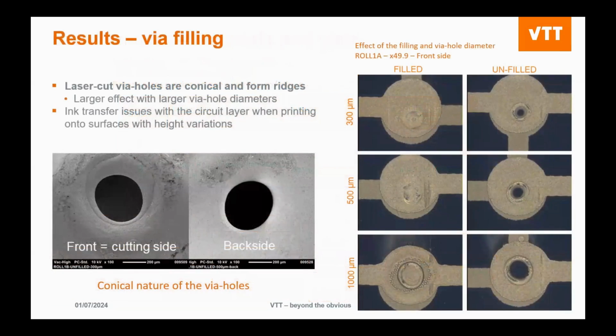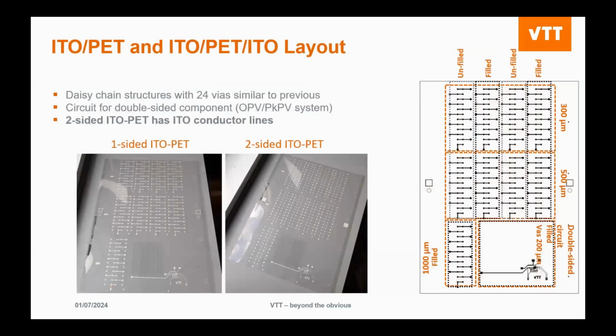So here are some examples of what the via filling process looks like. You can see, just from the diameter of the laser cut vias, that you also have a conical structure of the via, and this was also observed in the cross sections. When we're looking at ITO PET, which is indium tin oxide, we did an investigation with just a single layer of the ITO. Here you can see on the back side you'll have the ITO, and on the front side you have your daisy chain by the printed silver. But here we also have the daisy chain on a double-sided ITO, so you can see that the vias were filled with silver, but the interconnections between the via holes are the ITO, so that's why it looks transparent.